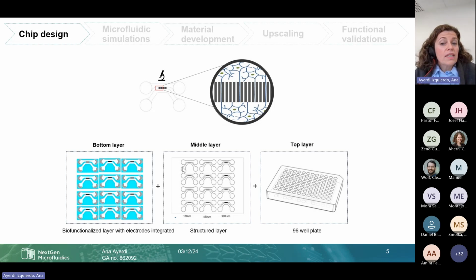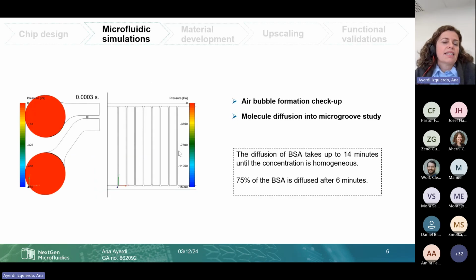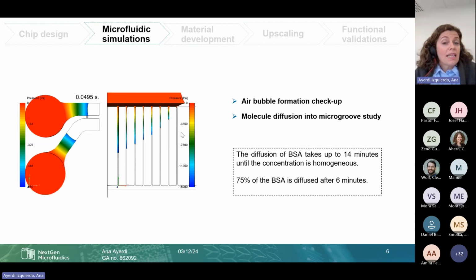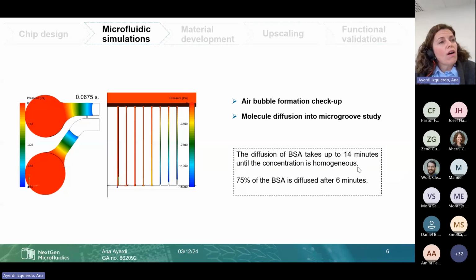Once the design was set, microfluidic simulations were performed to check the air bubble formation and to determine the molecule diffusion throughout the microtunnels. This simulation determined that the diffusion of BSA, which was used as a protein model, takes up to 14 minutes until the concentration is homogeneous throughout the chamber. Most importantly, 75% of the BSA is diffused after 6 minutes, which accomplishes the goal of nutrient delivery in a very reasonable time for these types of consumables.